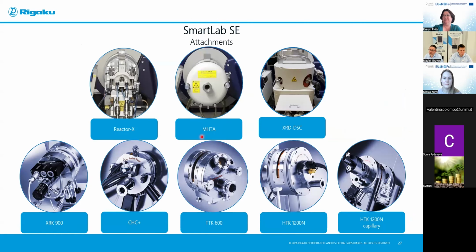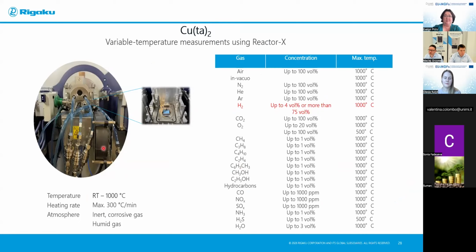And for non-ambient measurements, we have, for example, from Rigaku, special attachments like Reactor X, a multi-purpose high-temperature attachment, or the XRD-DSC attachment. As well, we can also install attachments from Anton Paar. I'd like to focus your attention on the Reactor X. Here we can heat the sample from room temperature to 1000 degrees with a maximum speed of 300 degrees per minute.